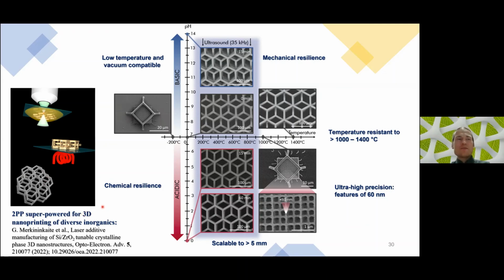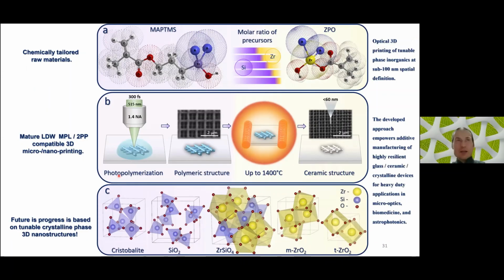Once again, two-photon lithography, or optical 3D printing at the nanoscale, is super-powered by diverse inorganic material choices. And here I come to a summary: by chemically tailoring raw materials and combining with already mature laser direct writing multi-photon lithography, we make an approach which is not specifically bound to our own equipment, but can work with other homemade or commercial setups. As a material, it can be 3D structured and later heated and converted into ceramic, and the ceramic or crystalline structures will depend on the heating protocol and, more importantly, on the inorganic ratio of precursors and, of course, the chemical elements themselves.